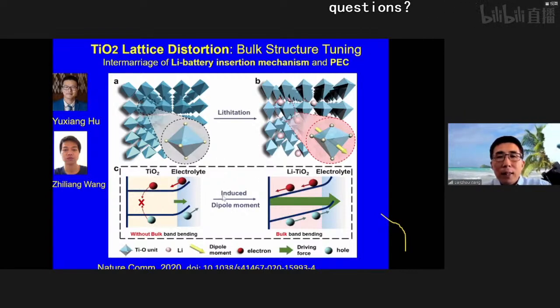And in this approach, we try to have a built-in electric field across the film. The idea we use is to insert some lithium into the TiO2 framework. They would only go to the void around here, not into the octahedral. But because of the insertion of the lithium, it will distort the octahedral of the structure, and then create some dipole moment.